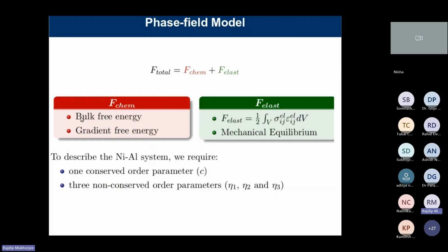The bulk free energy is what you get from the phase diagram and the free energy diagram. And the gradient free energy is related to your interfacial energy. That is the chemical part of the free energy. Whereas for the elastic part, when we try to calculate the elastic energy, we basically have to solve the mechanical equilibrium equation. And we assume that at every diffusion time step, the system is in mechanical equilibrium. Mechanical equilibrium is much faster than the diffusional process, because the atom has to move only a fraction of the atomic distance. So the elastic equilibrium is very fast, so we assume that at every diffusion time step the system is in mechanical equilibrium.